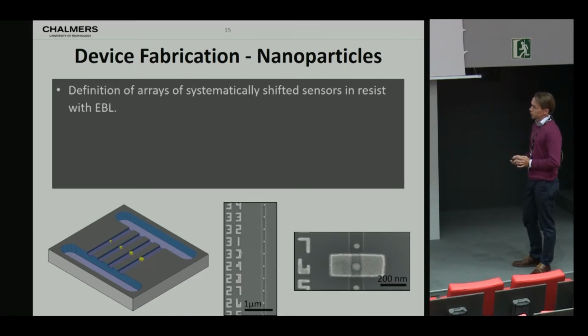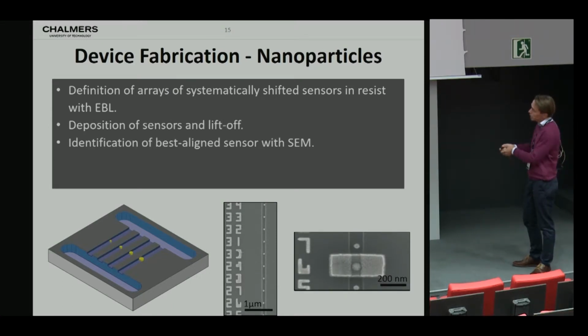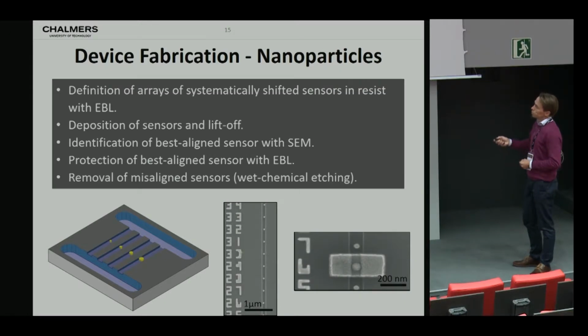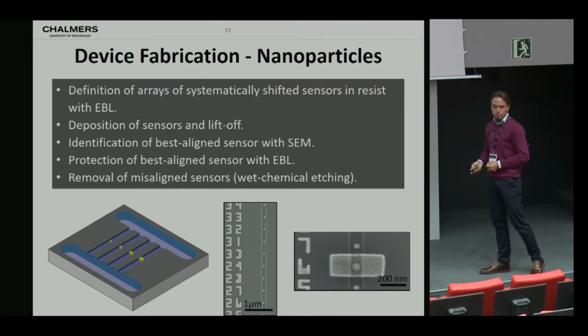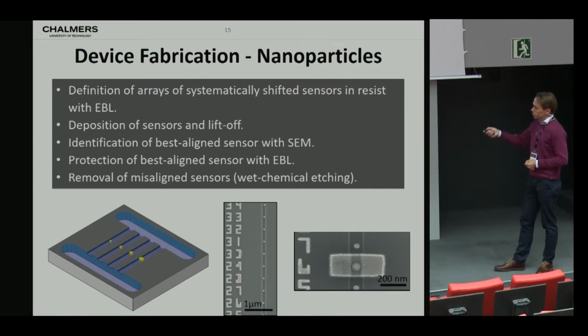Then, in the next step, we fabricate the nanoparticles in the predefined channels. To do this, we write arrays of systematically shifted, and that is important, sensor particles in the resist with EBL. We grow them, do the liftoff, and then using SEM, we identify which of these particles, which all are slightly shifted, has the best alignment with the channel. We apply E-beam again to protect the best aligned particle with resist, to allow us to then remove all the misaligned particles as well as these markers and so on by wet chemical etching, leaving us, if we want to, with a single nanoparticle which is perfectly aligned with the nanochannel.